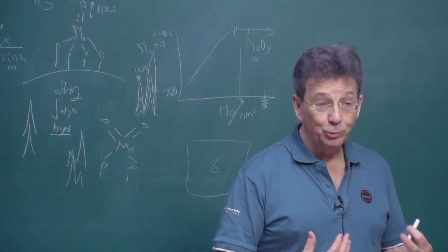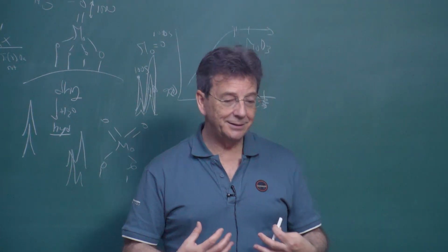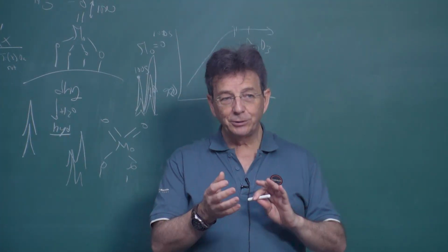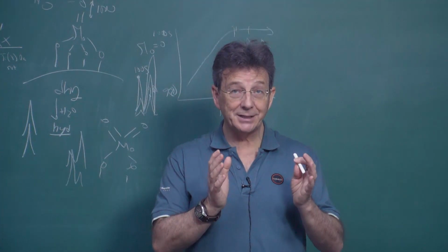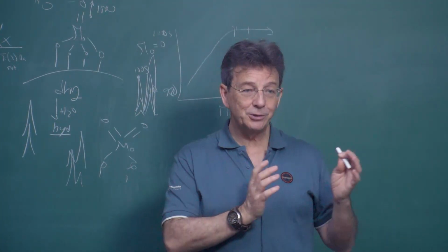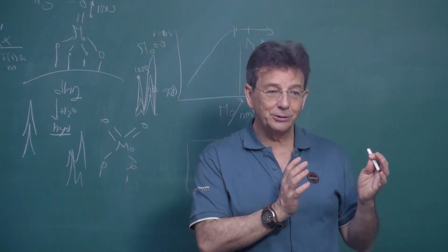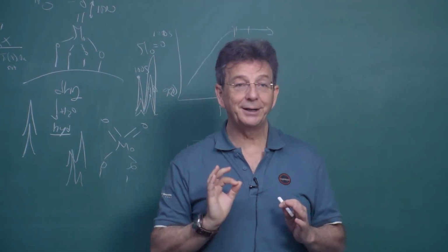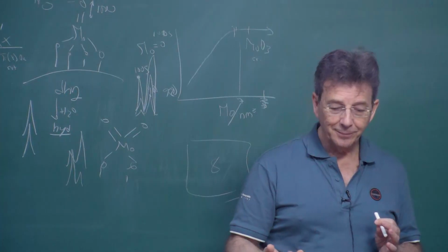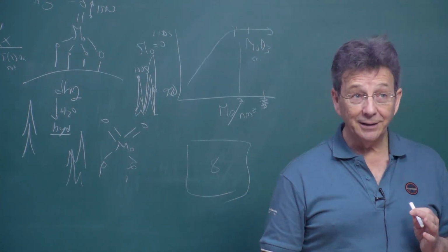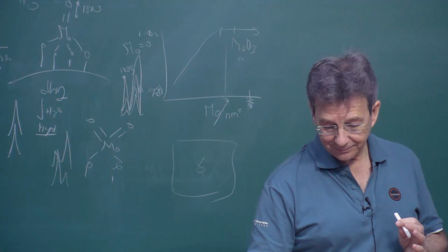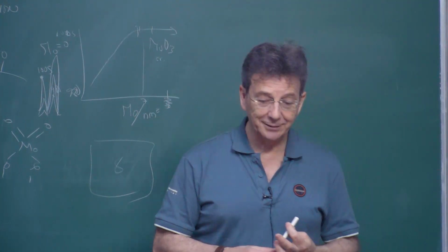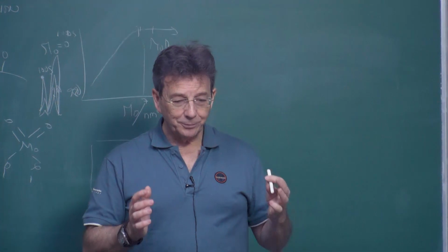Basically, by doing that, vanadium is catalyzing the transition of anatase phase to rutile, because vanadium substitutes titanium because they have a similar size but not identical. So it is substituting it, and by doing substitution, the lattice is not what it used to be. It's a little bit strained, and then you trigger the tendency to go into rutile at 600 degrees C and not at 1000 plus. So this is another kind of catalyst, a catalyst for the activation, but a catalyst anyhow.